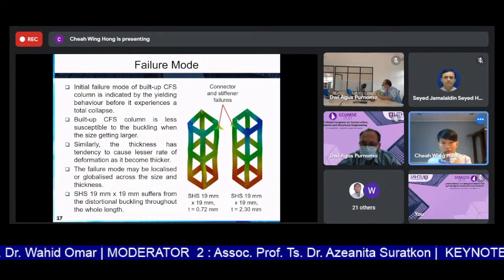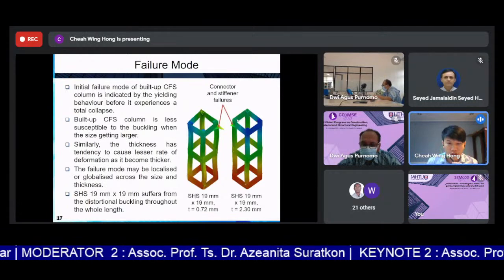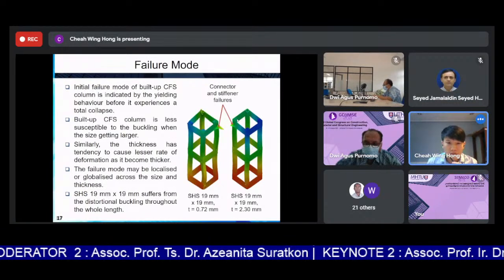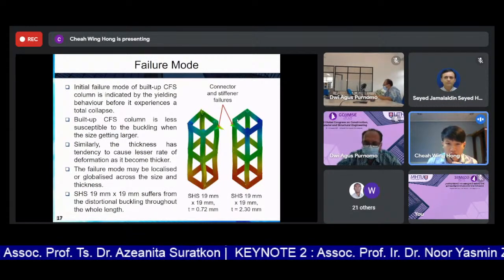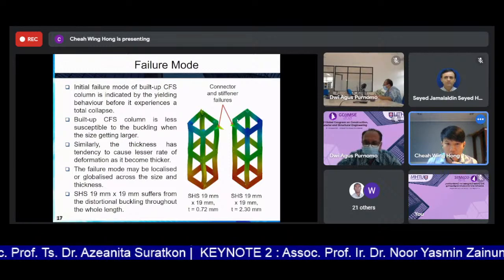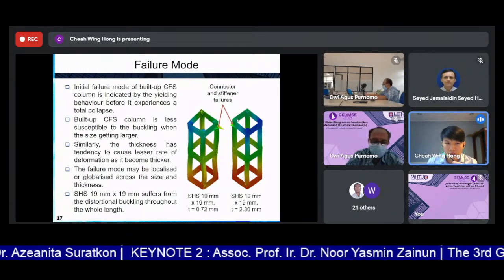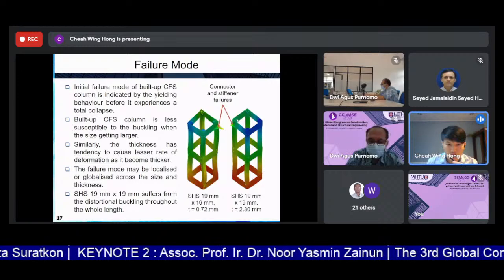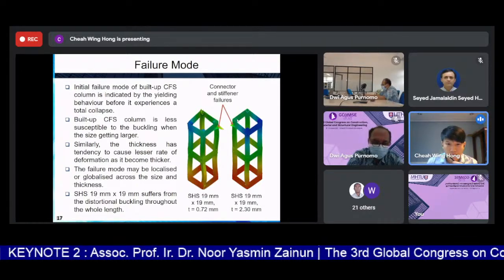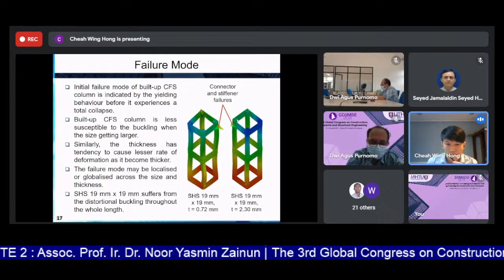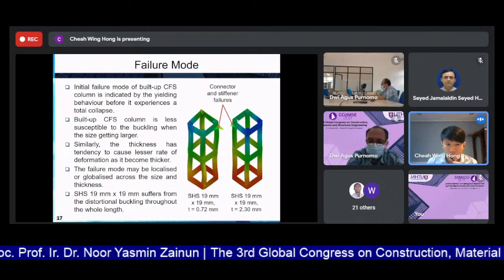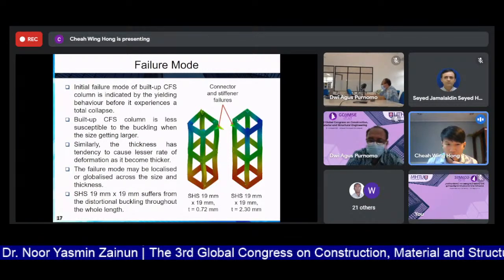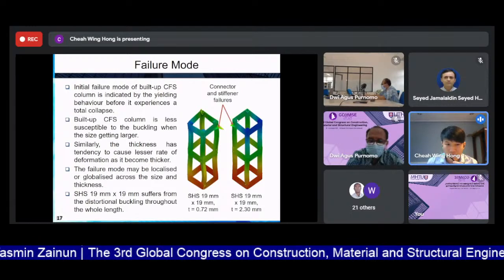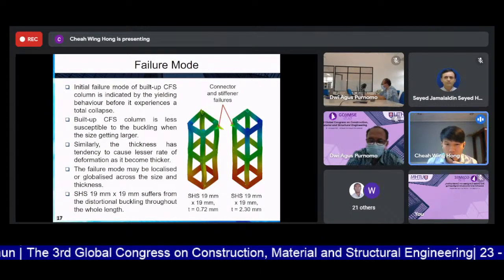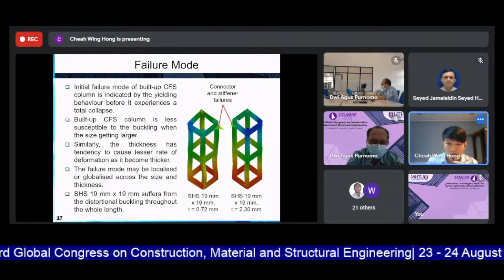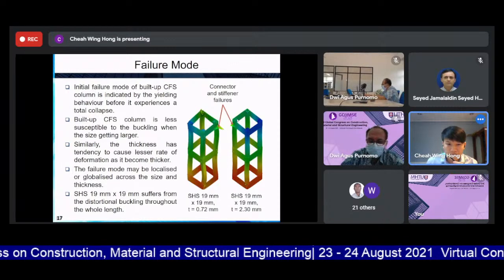And next will be the failure mode of the build-up CFS column. The initial failure mode of a build-up CFS column is actually indicated by the buckling behavior before it experiences the total collapse. So the build-up CFS column is less susceptible to buckling when the size of the build-up CFS column is getting larger. Similarly, the thickness will cause a lesser rate of increase in the deformation as the thickness of the build-up CFS column becomes thicker.